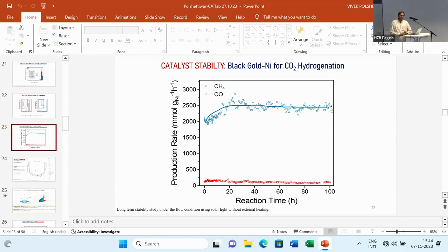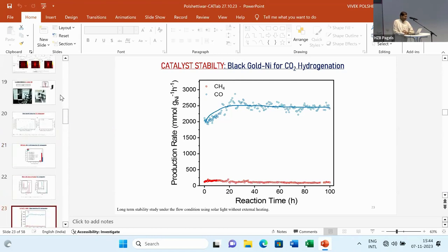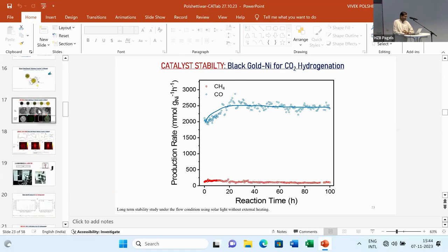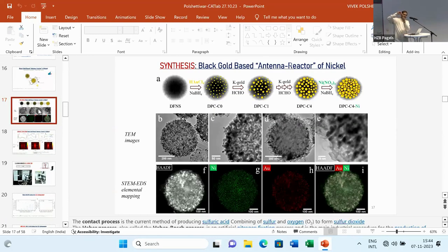And the second question is, when you use this nickel, you add a nanoparticle mixed with gold, right? What happens if you take this gold and make a layer of nickel on the surface, somehow by chemical reduction and so on? Why do you need a particle? Because I think if you make a layer, the electron injection from gold would be much easier, right? To take out the electron from gold. Very good idea, very good. So we wanted particles because the typical catalyst design was that the nickel nanoparticle will go only between the gaps so that gold remains free to absorb the photon. If I have a thin layer of nickel.